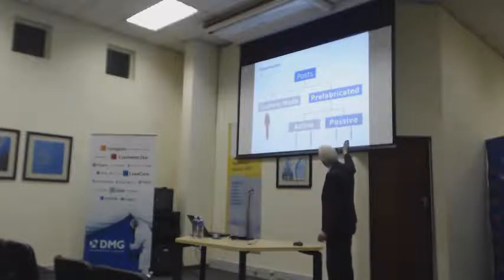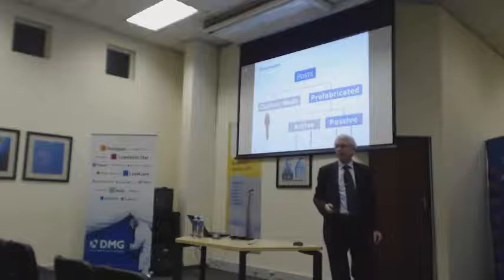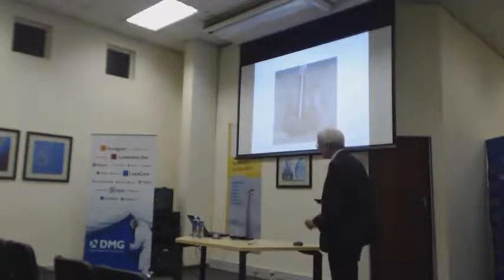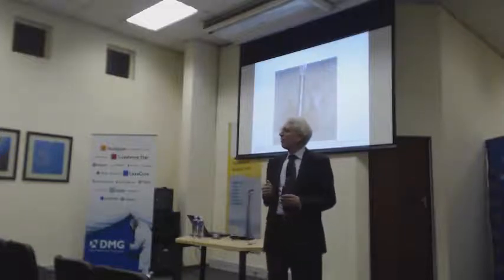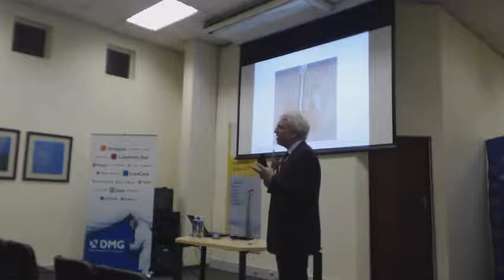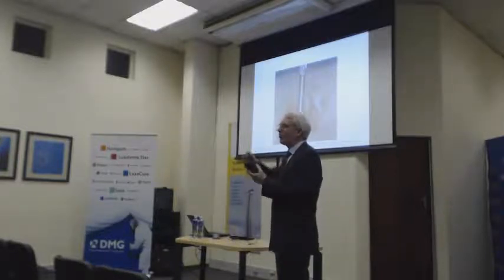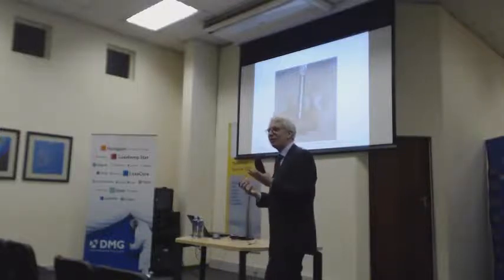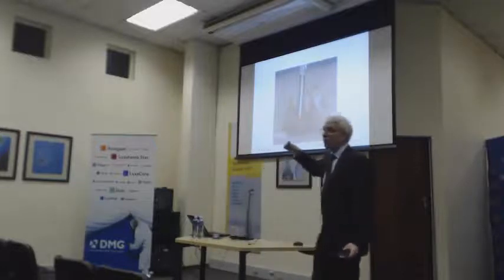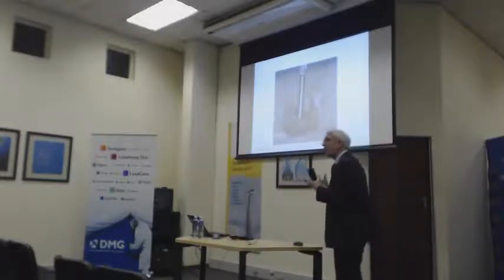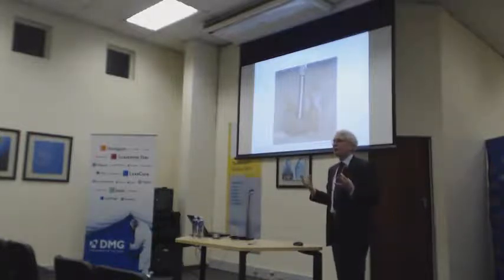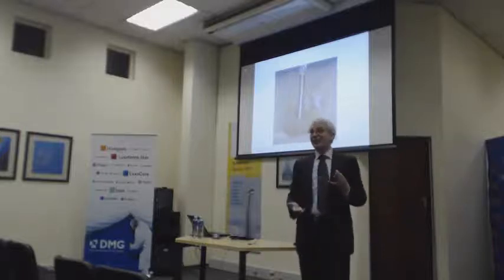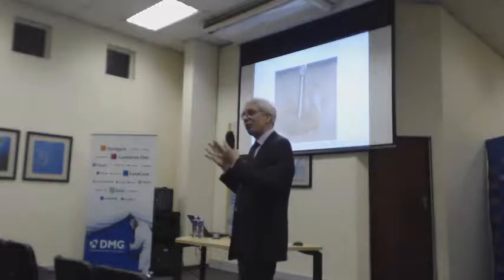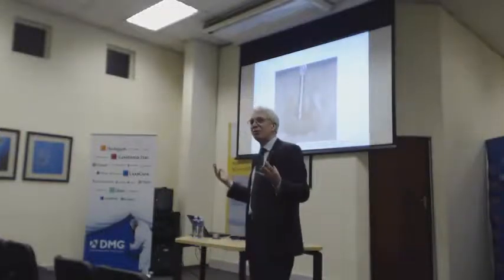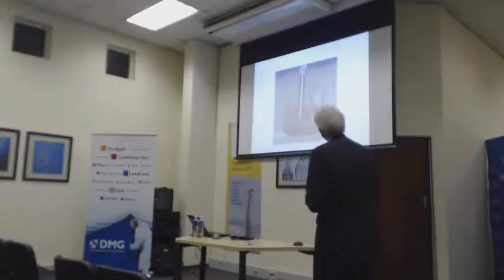So typically in Germany we are using either active or passive posts. And the active posts are naturally made of metal. So it's the screw. When I work at home, I sometimes have bad experiences when I want to put a screw into a board of wood, and it cracks because I didn't prepare the hole properly. The same thing can happen here. If you put the screw in, that process alone can lead to a fracture of the root. And this is totally counterproductive. You spend a long time using high-tech equipment to prepare the root canal and make sure that the root will survive. And then when you seat the post, you're cracking the root and everything is in vain. So this is a bad experience.